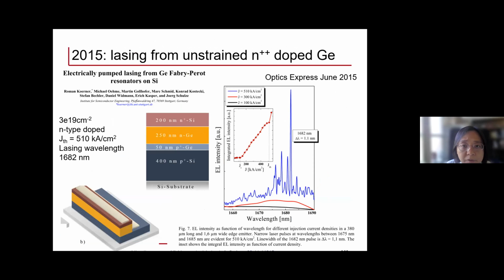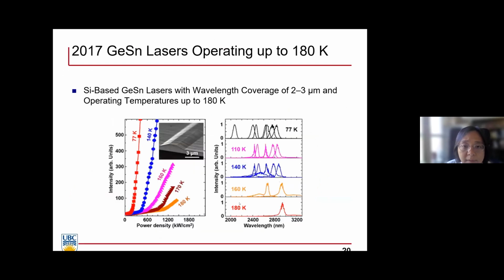And the second demonstration is from a German group. So here is an N-type doped germanium, with a nucleation layer on a silicon substrate. And lasing does happen. Of course, these initial studies show very poor germanium laser performance, but it's two demonstrations so far.